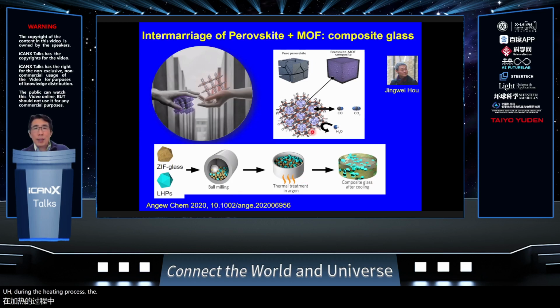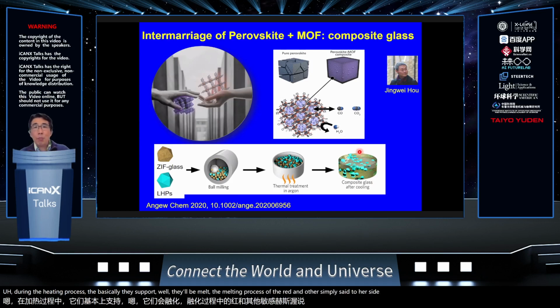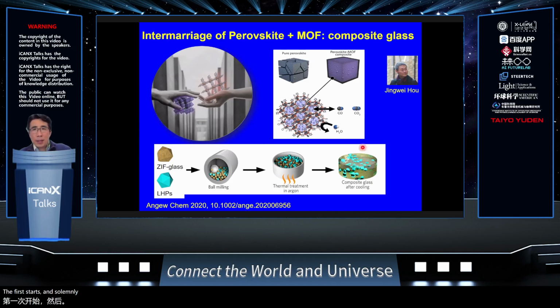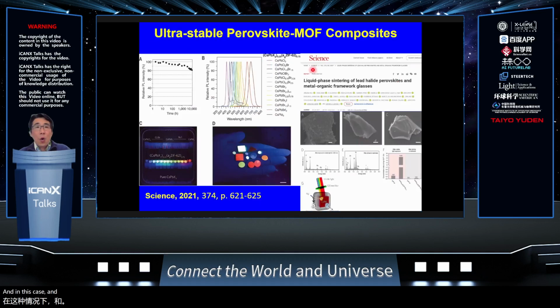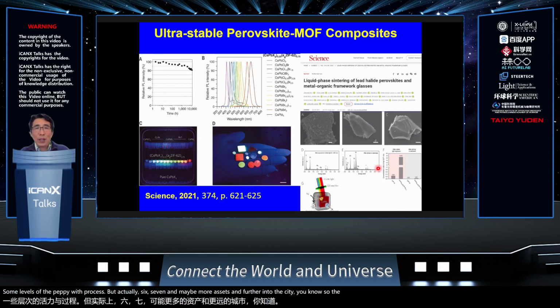During the heating process, basically this material will be melting. The melting process will wrap the surface of the perovskite to protect it from being attacked by moisture, by the water, and in this case we can realize a very high stability in this composite. For example, we put the composite into water for up to 10,000 hours, and we still keep over 80% of the PL emission. We also can tune the composition, the size and the shape, or the color, the light emitting color here, which can be stable for a very long time. This material also has some level of photocatalytic activity, but we certainly need more effort to further improve the photocatalytic performance in this regard.